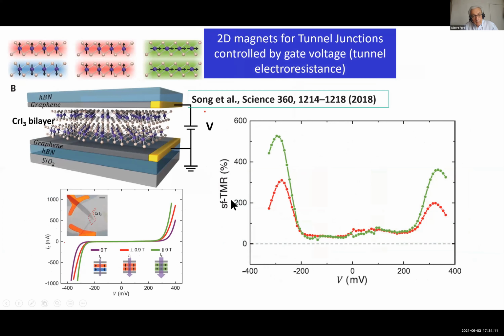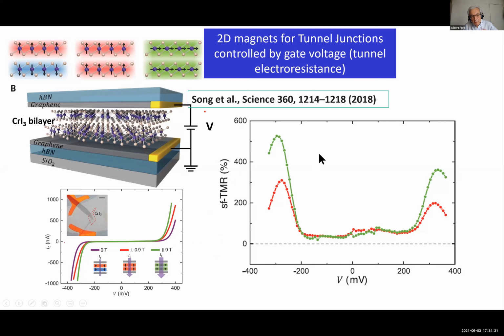So in fact, influence of electric field. In this sort of tunnel junctions, you can also obtain the TMR not by applying a field and changing the relative orientation, but by applying a voltage between the top and bottom electrode. So the best example I have found, I have not found a very clear example of this effect, but it is in a theoretical paper based on a quantum transport modeling of the transport property. So for this system with a layer of CrI3, a bilayer with an anti-ferromagnetic interaction.